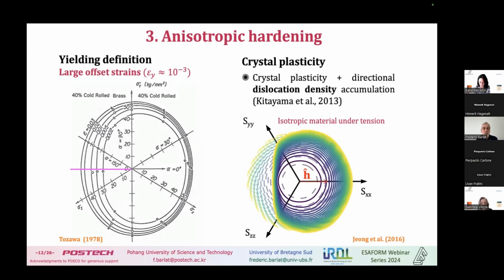But I show you two examples where one is experimental, the other is more model based on crystal plasticity. So it looks like a distortion is a good model to describe this. And this is the reason why we decided to go this way, only distortional, because to try to simplify, if a material model is too complicated, it's very difficult to use in practical application. And that's why we try to remain as simple as possible, although when we start to have nonlinear strain paths, it cannot be that simple.